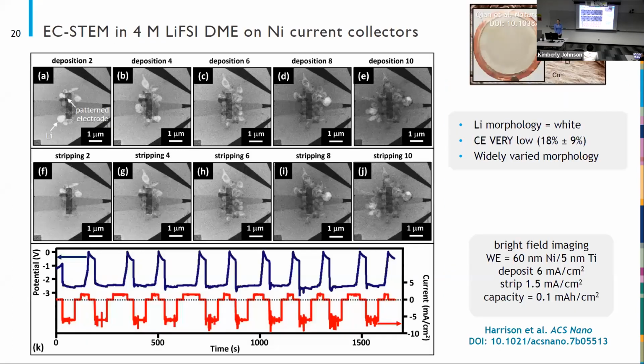So these are the types of images that we're able to get from these STEM experiments. These are bright field STEM images. So we have white lithium that's shown here, and the darker colors are for denser metals. You can see that we're able to grow lithium on these electrodes. And then when we try and strip that lithium away, we see a lot of it ends up still on the electrode, and we're not able to get rid of it, which means that there's dead lithium forming, and our coulombic efficiency is very low.